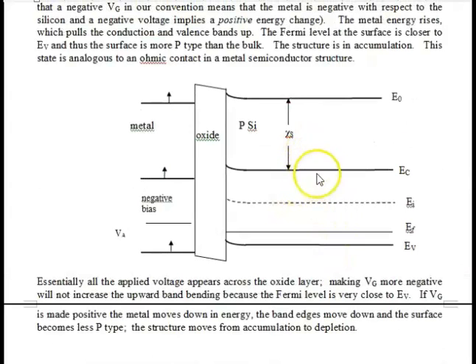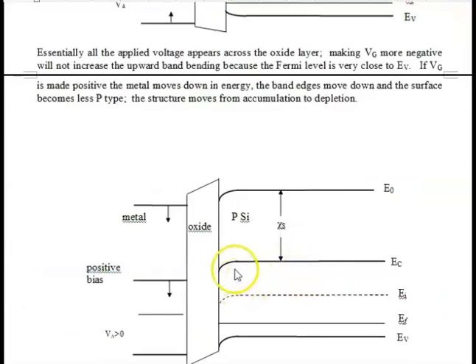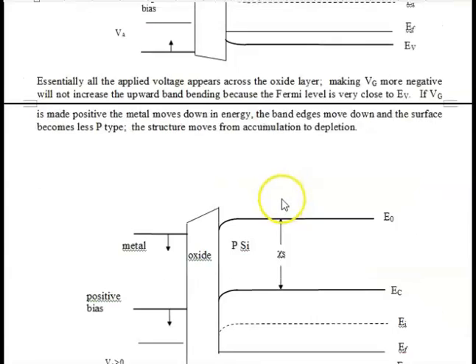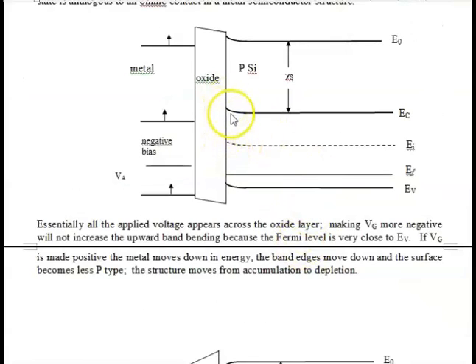And you say, well, this looks pretty similar, except the bands bend up here and the bands bend down here. How do I know this is accumulation? And how do I know this is depletion? Because here, the surface right at the oxide silicon interface is more P than in the bulk. Why? Because the Fermi level is actually closer to the valence band. Here, this distance is 0.42 eV, and so whatever this distance from here to here is about 0.56. So whatever that difference is, I don't know, 0.18 or something, it's closer here. So it's more P here than it is here, and therefore we have positive charge at the interface, and there is no depletion